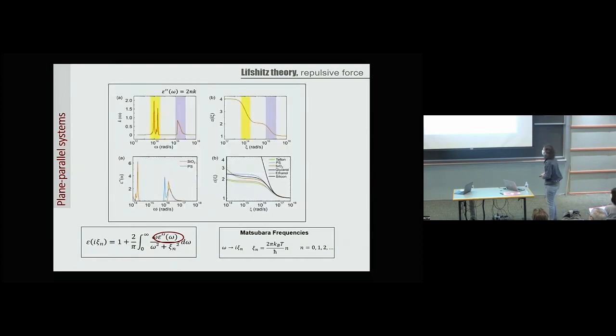In addition, some of the intuition that at least we could have with the solar cells and things that we were doing was missed. For instance, if you have a look at the extinction coefficient here, which is related just to the imaginary part of the dielectric permittivity, anytime you have high absorption peaks, your curve in Matsubara frequencies will have these steps here, whereas when you have a flat curve, you have these plateaus here.